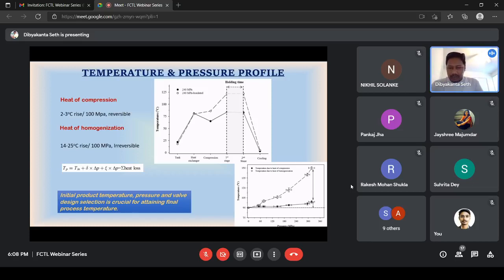So in the second one, the bottom one in the graph, you can see that the dashed line is the heat of homogenization, and the solid line is the heat of compression. So this is the difference. A very huge difference: the initial product temperature was 90 degrees Celsius in this particular system. Now they could achieve up to 150. That means there is a 50-60 degree rise in the temperature.